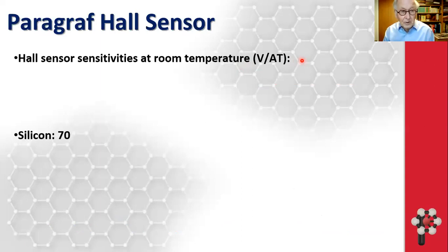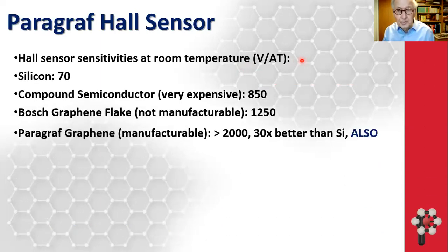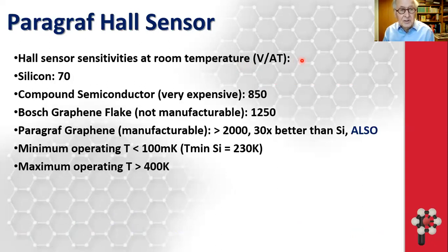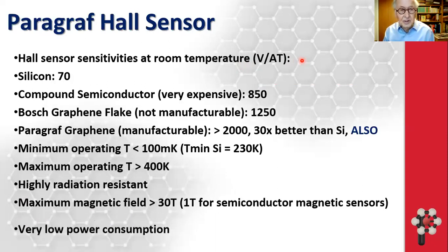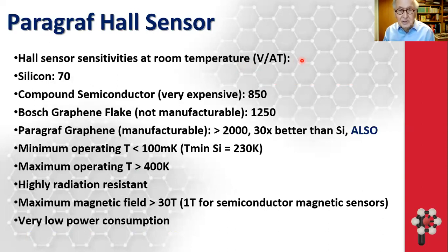Hall sensor sensitivities are measured in units of volts per amp Tesla. A silicon Hall sensor has a sensitivity of 70 volts per amp Tesla. Compound semiconductors like gallium arsenide, you can have quantum well Hall sensors made out of those, and they were the best ones before graphene came along, with sensitivity typically 850 volts per amp Tesla. The Bosch graphene flake, if you read their paper, was about 1,250 volts per amp Tesla. Our graphene Hall sensor, which is manufacturable, is better than 2,000 volts per amp Tesla. So 30 times better than a silicon Hall sensor.